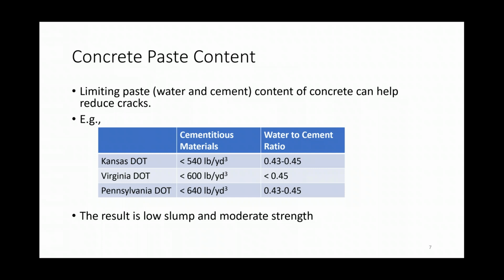There were some concerns from some DOTs that you don't always get what you specify. So it's good to shoot a little higher just in case there's material quality issues. Because of that, some states do want to specify higher strengths, but others are comfortable with moderate strength. They do experience less cracking with less cementitious material content.